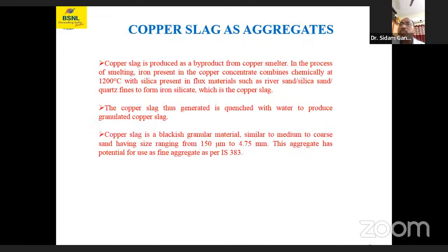Next, copper slag as an aggregate. Copper slag is produced as a byproduct from copper smelters in the process of smelting. Iron present in the copper concentrate combines chemically at 1200 degrees Celsius with silica present in the flux materials such as river sand or silica and quartz fines to form iron silicate, which is the copper slag. The copper slag thus generated is quenched with water to produce granulated copper slag.